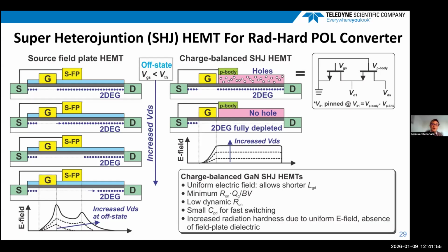While the super heterojunction consists of the p-type gallium nitride material deposited on the aluminum gallium nitride HEMT structure. And this device basically consists of the conventional AlGaN HEMT and a vertical PN diode. And we designed the magnesium doping concentration in the p-GaN to match that of the 2-DEG, which we call the charge balance. In such a device, when you increase the drain voltage at off state, when the PN diode reaches the pinch-off voltage, the entire 2-DEG under the p-type layer is depleted.